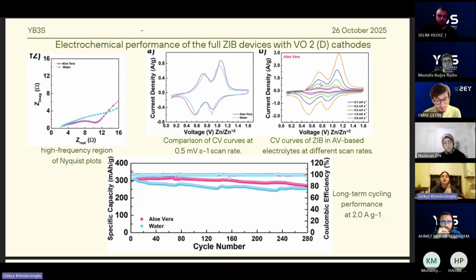And at the last, for the realization of this electrolyte, they made tests with vanadium dioxide cathodes. In this first picture, we see the lower charge transfer resistance in aloe vera than in the water, aqueous electrolytes. And the CV plot is a typical plot for vanadium dioxide.